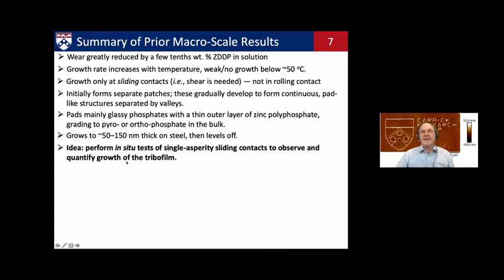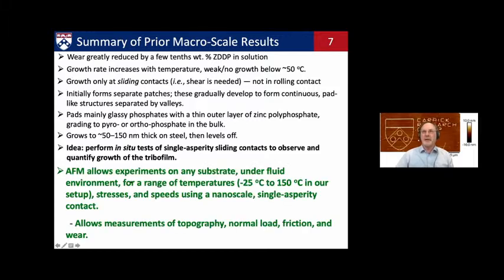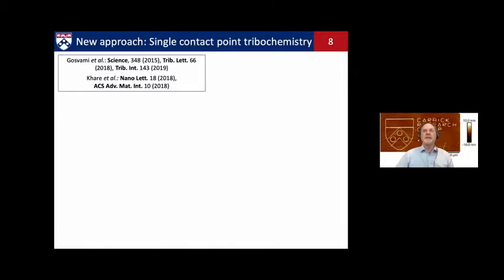So to get at this more deeply, we decided to do some in situ tests using AFM in single asperity contacts. The advantages of this method in general are that you can use almost any substrate as well as a variety of tip materials. You can work under fluids, you can vary the temperature, you can have a range of stresses that can reach very high values to match experimental conditions, and you do have a range of speeds, although they tend to be quite a bit slower than the macroscopic applications. And you do this all in a nanoscale single asperity contact, a well-defined contact where you can measure topography and control the load, measure friction, measure wear if it is occurring.